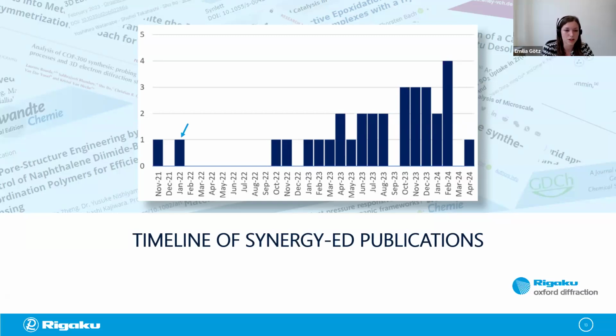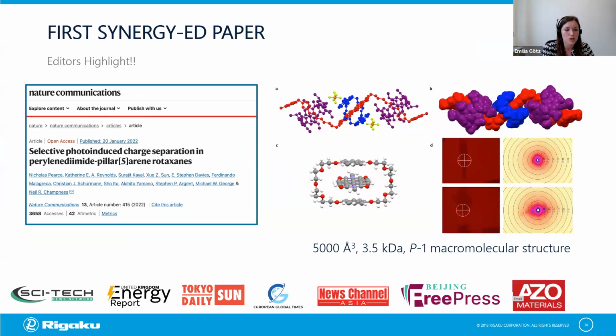The second one from January 22, however, was this one by Pearce et al., which got published in Nature Communications as an editor's highlight. And they used 3D-ED because the crystals were only diffracting very poorly in single crystal X-ray diffraction. With electron diffraction, they managed to solve this pretty large macromolecular structure with a volume of 5,000 cubic angstrom and a P1 bar symmetry, which you can see here. And over here, the crystals used for structure solution are shown with their respective diffraction patterns.